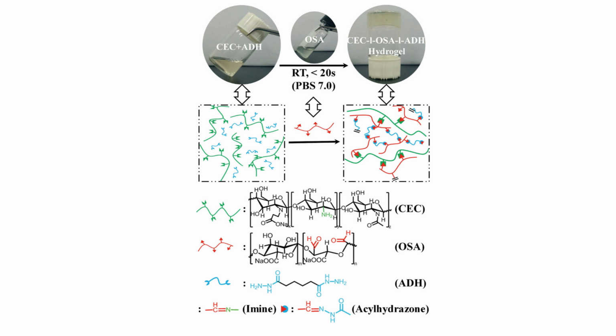It can therefore be concluded that the addition of aniline or pH adjustment can lead to self-healing of materials containing reversible acyl hydrazone bonds. Scientists developed a novel polysaccharide-based self-repairing hydrogel. The hydrogel network exhibited dynamic acyl hydrazone and imine bonds, enabling dynamic fracture and reorganization to occur under mild conditions. The self-healing capability of the hydrogel was substantiated through macroscopic self-healing tests, rheological recovery tests, and analogous methodologies. The hydrogel demonstrated a healing efficiency of up to 95%, a feat accomplished under conditions devoid of external stimulation.